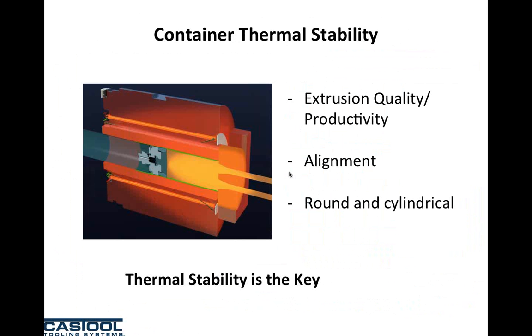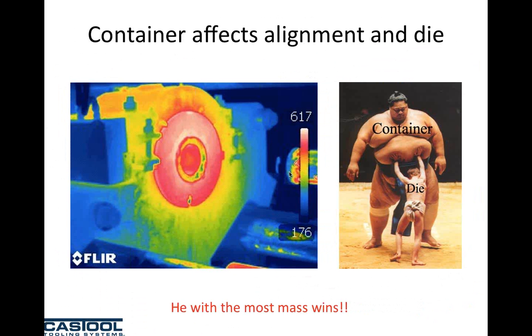If we take a look back at our external heating, and actually we'll go with this one. A lot of extruders that I visited last week operate 6 days a week. On Sundays, basically, they set their liner at 800 and some odd degrees Fahrenheit, and the heating elements are running between 1300 and 1400 degrees. So by Monday morning, the container housing is easily 800 degrees, if not 900 degrees. When the container housing is hot, it actually lifts the container and ruins the alignment between your container and your die and your container and stem. So it's not just about temperature. Temperature also affects mechanical alignment.